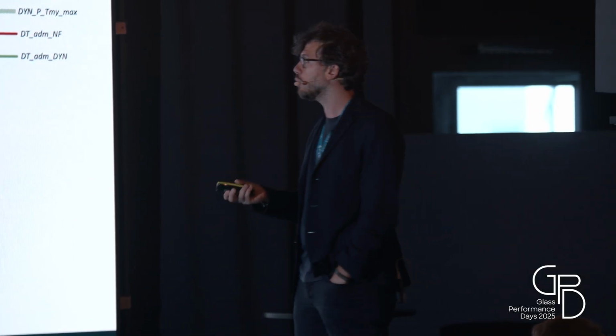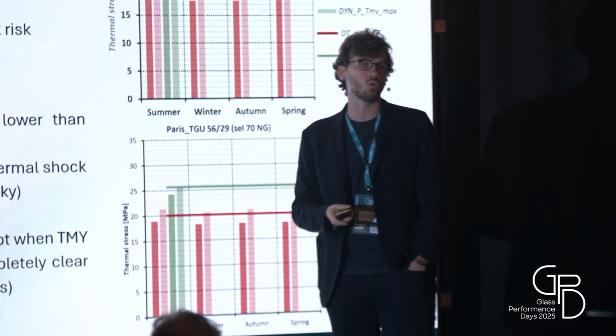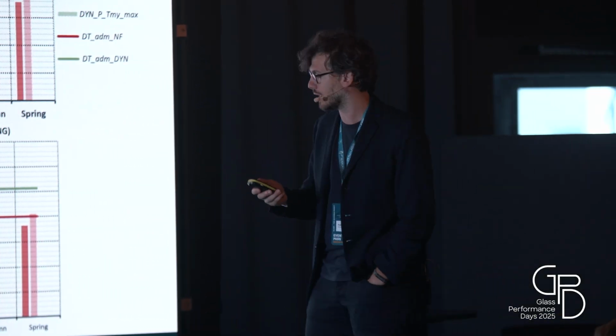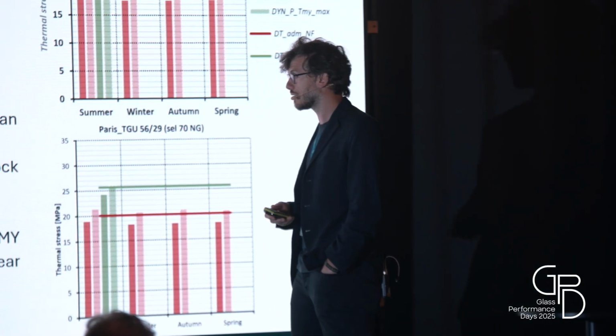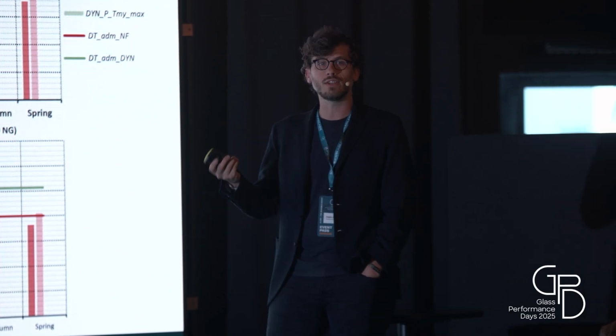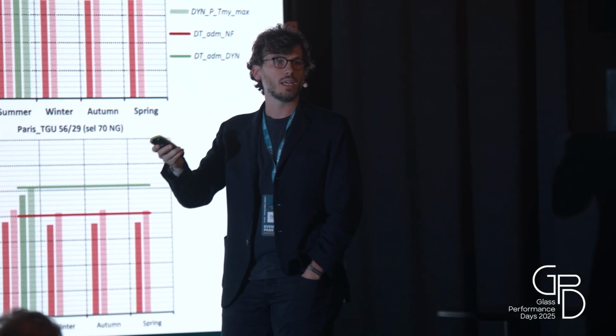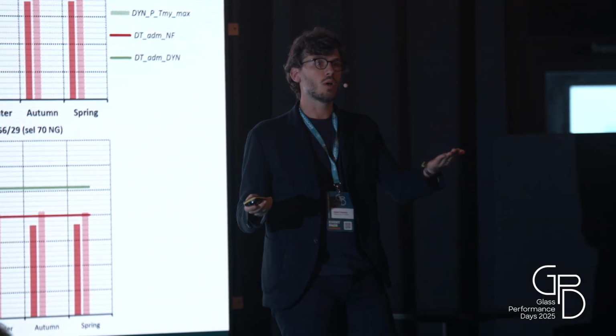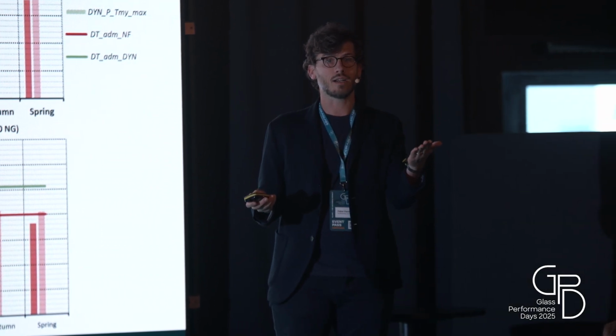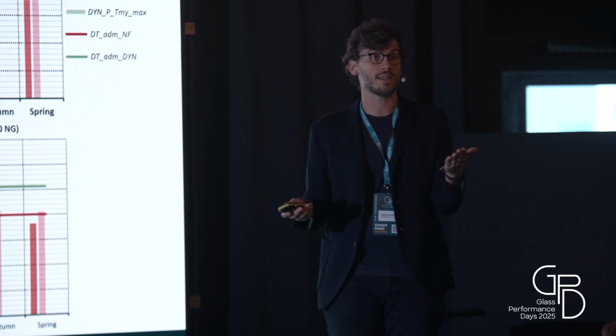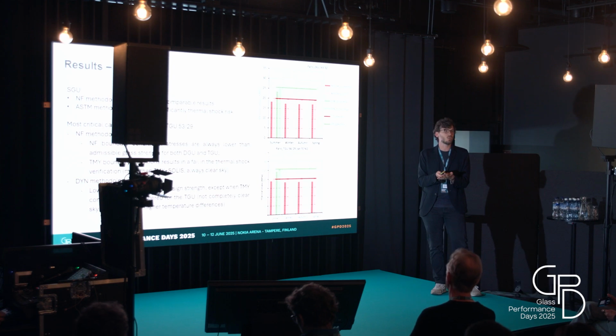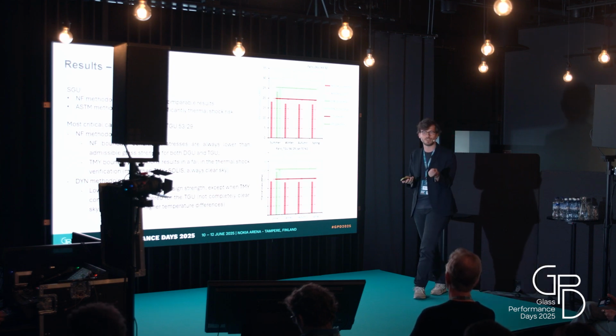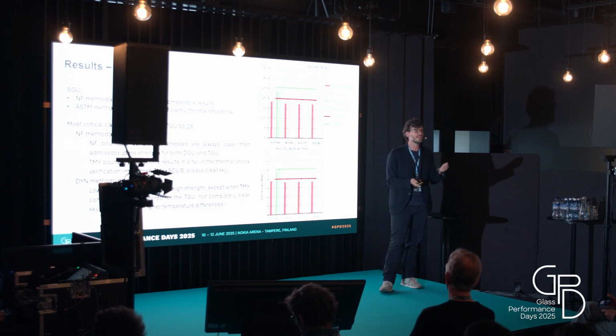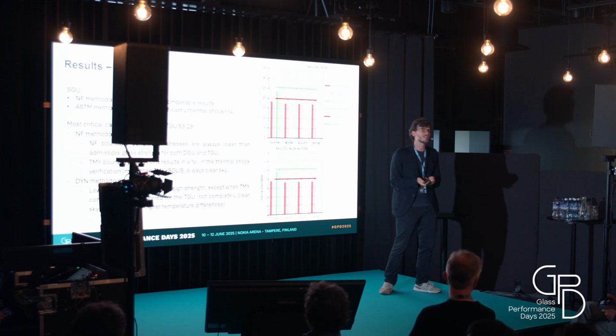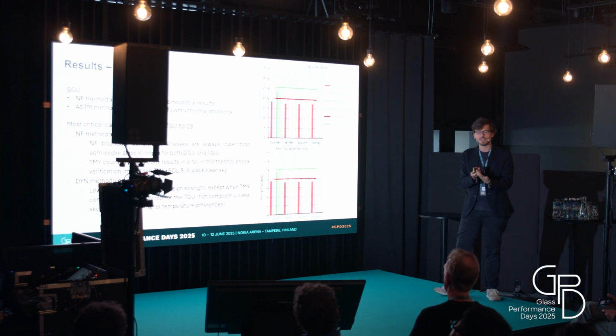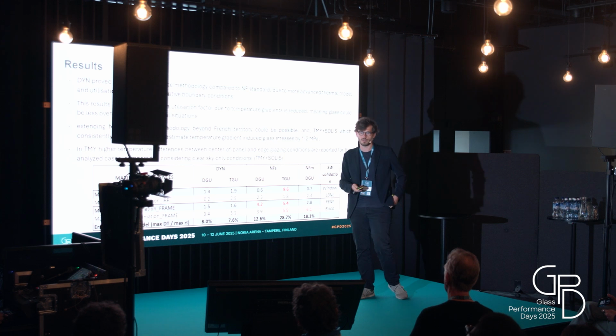these stresses are normally lower, the thermal stresses, compared to what the national standard methods are predicting. So in a way with these methods we are able to predict more accurately what the delta T is, but on the other side we are using boundary conditions that potentially are more stressing in terms of thermal shock risk assessment. But the combination of the two makes us use a methodology that is more precise, so we are able to quantify in a more precise way the utilization factor, and we can use it to engineer the glass better, rather than not knowing what is really happening in terms of boundary condition and in terms of delta T.